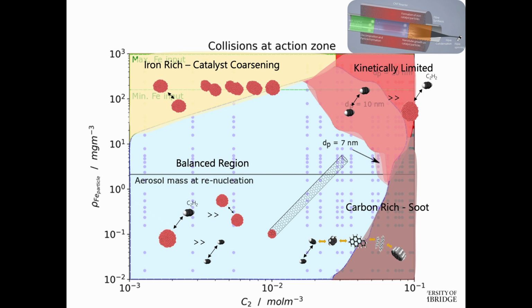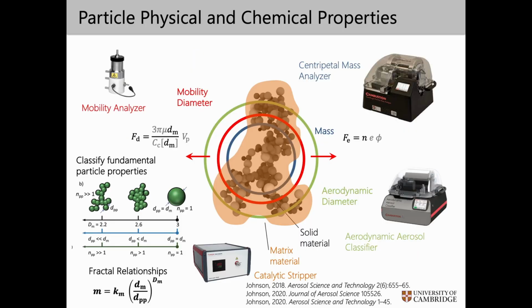And if we go up and to the right, where we put commensurate amounts of carbon and iron in, we ultimately enter a regime where we're kinetically limited, where two acetylene molecules collide with one another slightly faster than what we would like, which is an acetylene molecule colliding with an iron particle. And that collision, to first order, is the dominant reaction pathway in this system. So we can measure collision dynamics. One way we do that harkens back to what our group has spent some time developing, a number of different measurement principles.